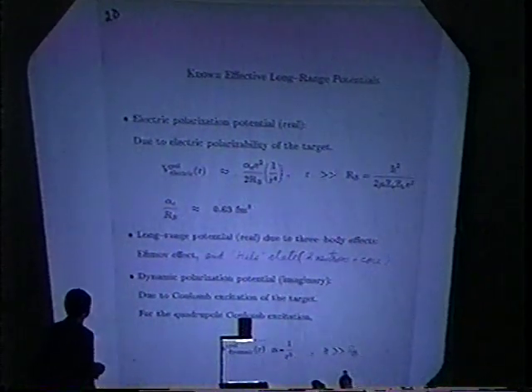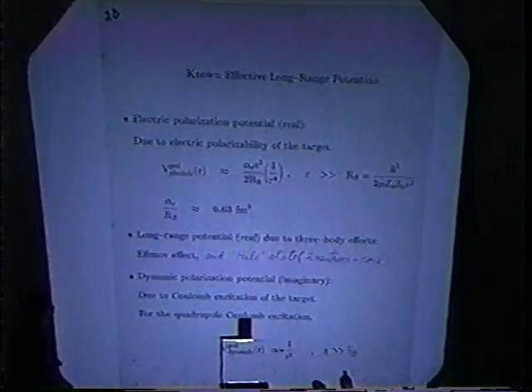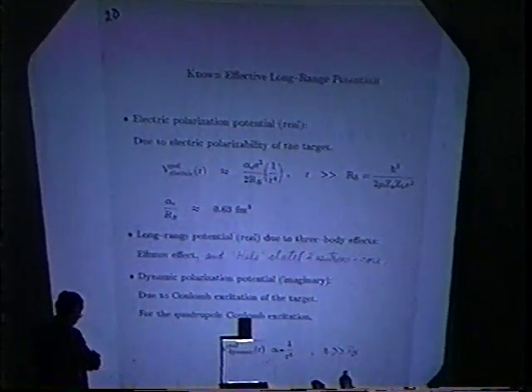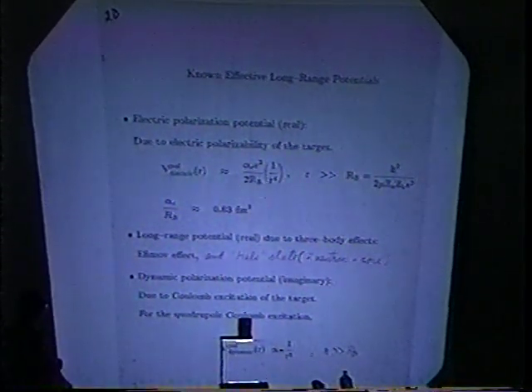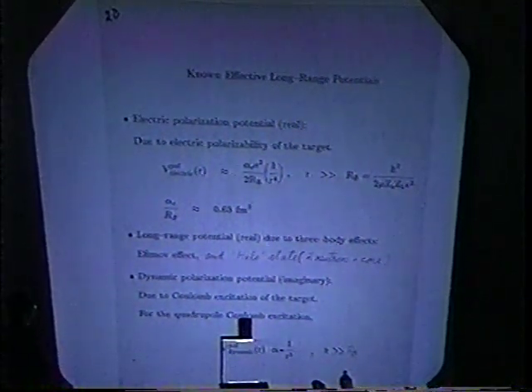So now the question is, does nature allow us to have such a long range force? Now there are no long range forces. Remember, this is a long range force in the imaginary part of the elastic scattering potential. One of the well-known potentials is the so-called electric polarization potential, which arises when two charged particles collide, they polarize each other electrically and create a new type of effective interaction. And that has a 1/r⁴ long range structure instead of a very sharp Yukawa cutoff. But this doesn't help us because this is the real part of the elastic potential.